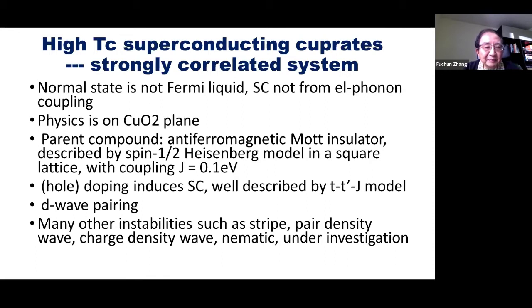And the basic physics is on the copper-oxygen plane. The parent compound, such as lanthanum 2 strontium copper oxide 4, is an antiferromagnetic insulator, well described by the spin-1/2 Heisenberg model on a square lattice with the coupling J about 0.1 eV. And hole doping induces superconductivity, which is quite well described by the t-t'-J model. And for high TC, it's not s wave, but a d wave pairing, evidenced by a number of experiments.